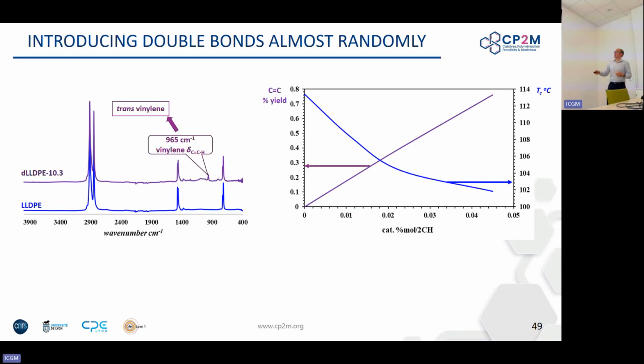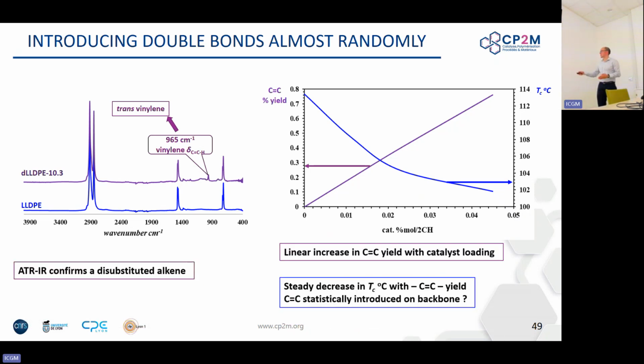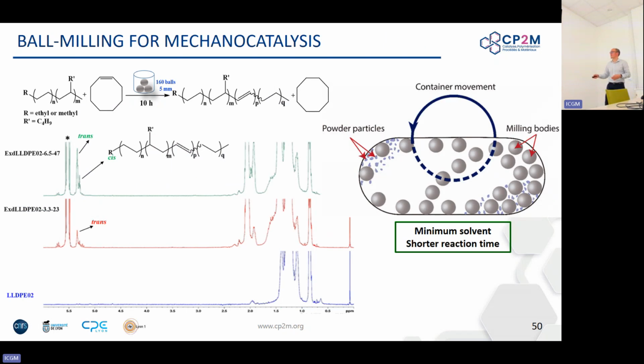Something that we do also is to follow where we locate these double bonds, and they are statistically distributed. So there is a continuous decrease in crystallization temperature when you increase the amount of double bond, okay? And when you chop them also, you can confirm that there is a statistical distribution of these double bonds. You can do this process in a ball miller. You need a hydrogen acceptor. It makes it more efficient.